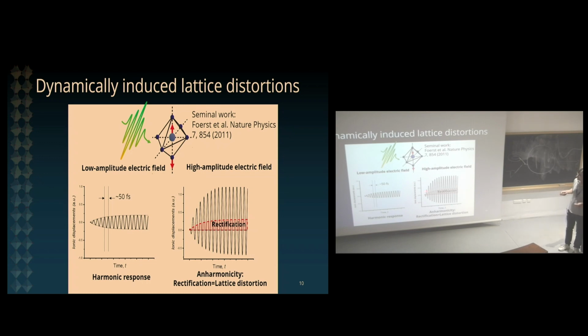Okay. So what happens is that the lattice is displaced along a Raman active coordinate, starting from a large amplitude excitation of an infrared active phonon mode. Okay. So if you want, it's a way to induce out of equilibrium lattice distortions.